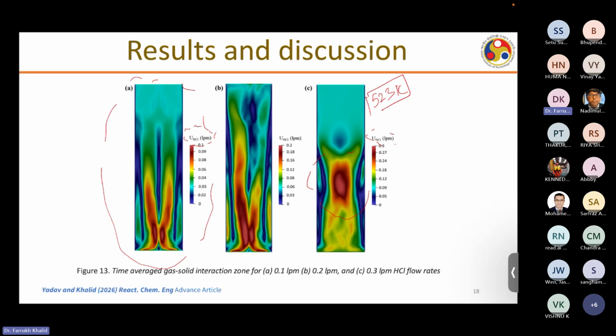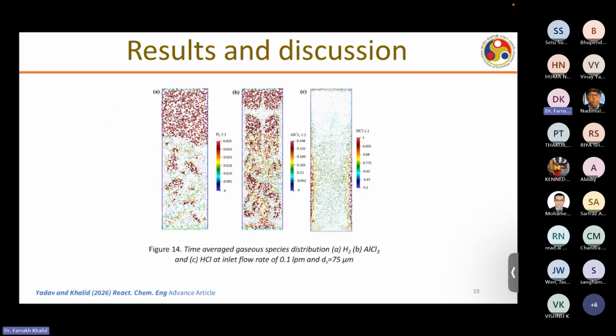As I was mentioning about the material challenge, we were looking for a material that can sustain around 600-700 degrees Celsius and also handle this HCl gas. We tried different things, and we found that a nickel-based material was a good one. We purchased the reactor from one of the companies, but we gave our design and everything. It is nickel based, not stainless steel, because stainless steel will easily corrode. However, in other salt applications, we are using it.